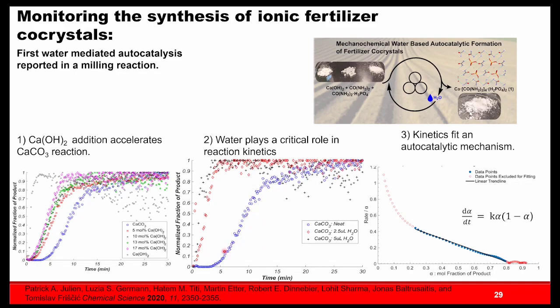But what I think is striking is the amount. In this case, we took calcium carbonate, and at a 200 milligram scale, we added 2.5 microliters of water, and we have a massive change in the reaction kinetics. Furthermore, if we take our calcium carbonate data, we can fit it to an autocatalytic rate law. For the middle portion of the data, it nicely fits an autocatalytic reaction rate law. So we found that this is one of the first detailed kinetic evidence that water autocatalysis is a thing in mechanochemical reactions, and that it's very important in certain reactions.